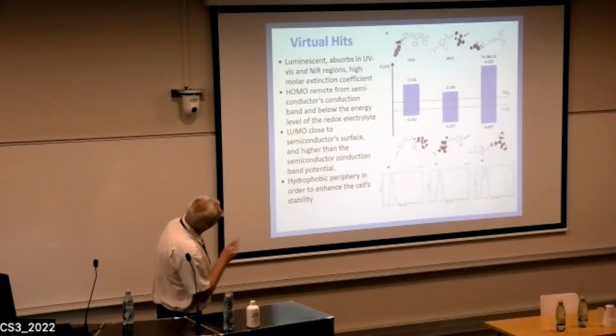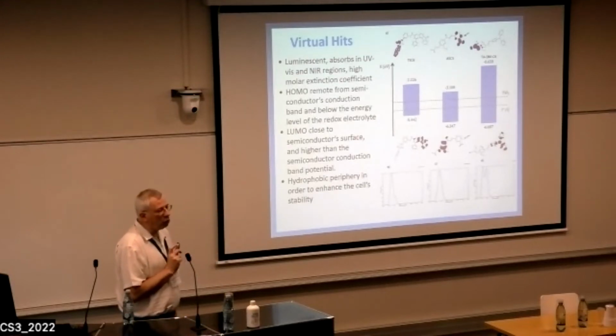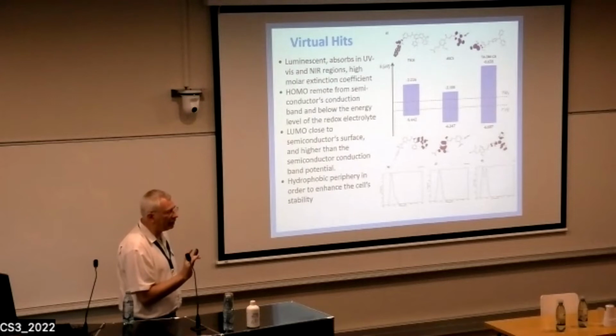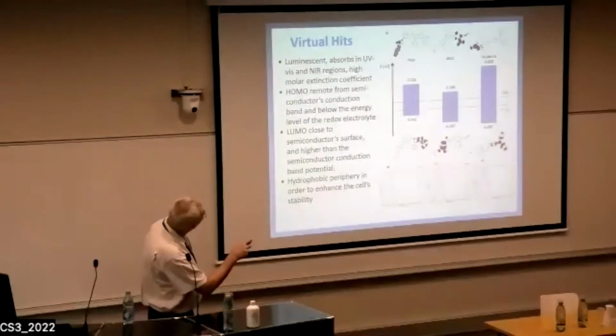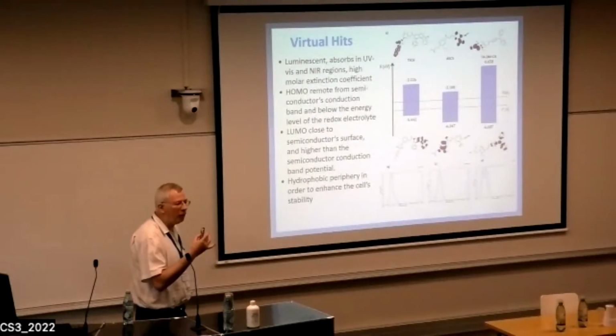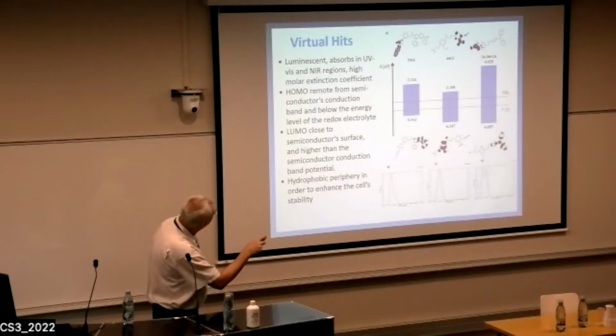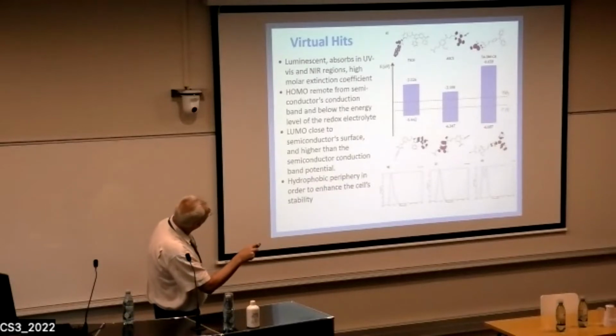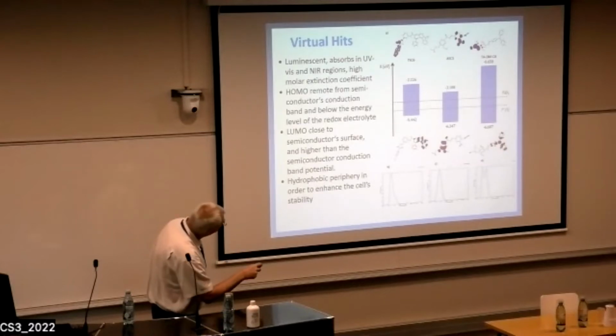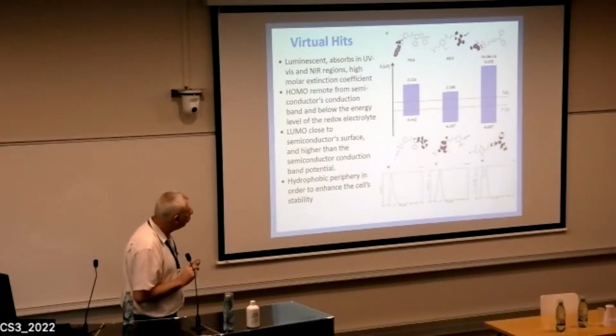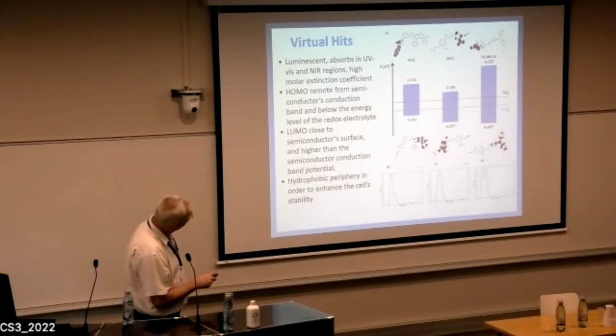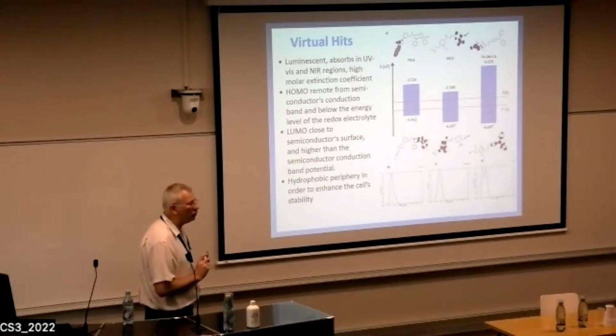And here on the right, I'm showing a compound which is a very active one from the database. So we ran the same set of calculations on all of them. Actually, we ran on many more compounds, but I'm just showing some examples. And these compounds meet the criteria. This is their absorption spectra, which we didn't like that much because we wanted it to be shifted a little bit more to the right.